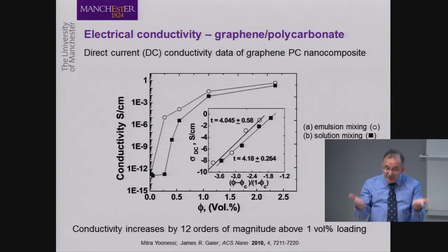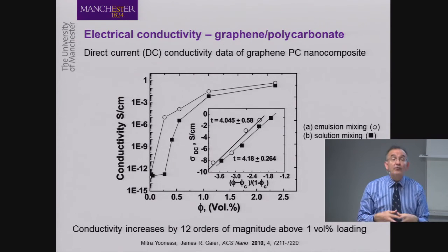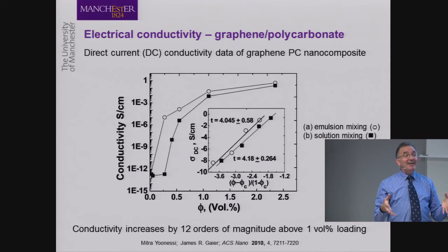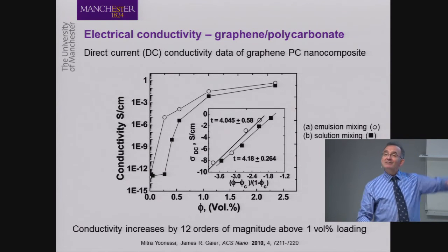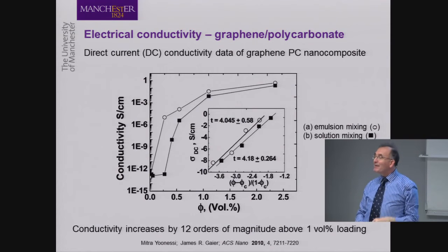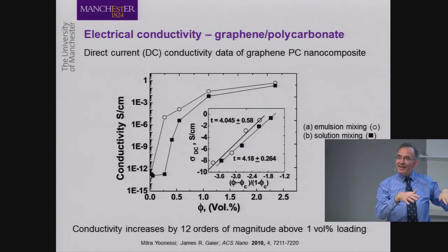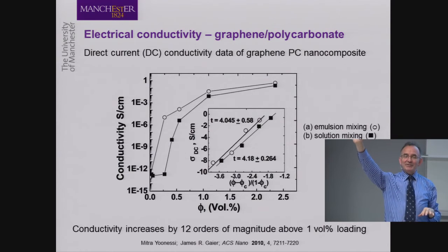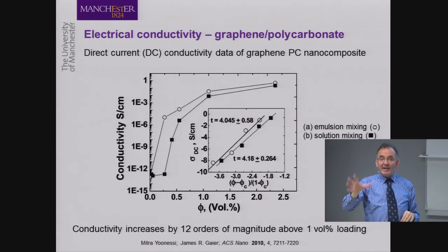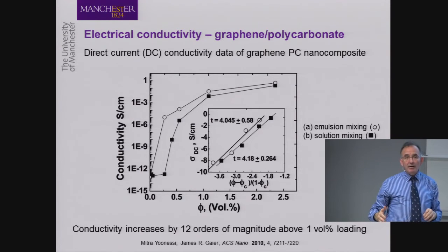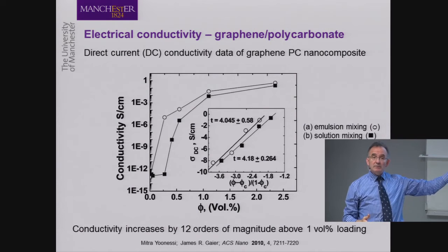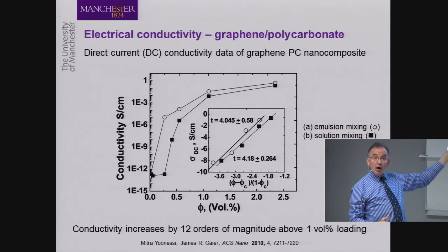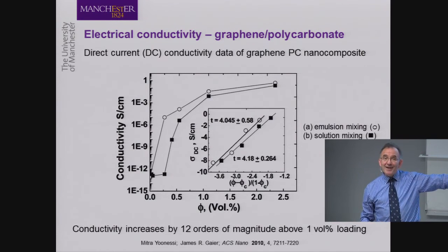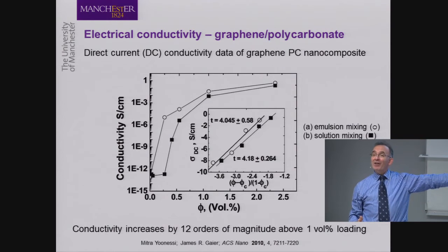So that is a significant improvement. Of course, someone might say the electrical conductivity of copper is 10 to the power of 7 Siemens per meter, which then again, I'm far, far away from that conductivity of copper. Now, the conductivity of the pure graphene flake on its own is similar to copper, but when you mix it with the polymer, then obviously it's much lower, but still 12 orders higher than the monolithic polymer.